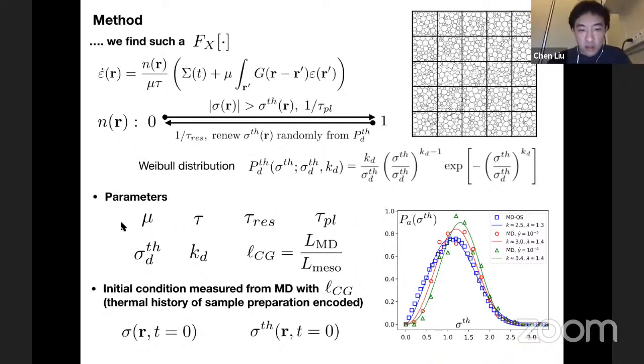So to summarize, we have these parameters. There are quite a lot. The first one is the shear modulus. The second one is the time scale that fixes the local viscosity when there's a plastic event. And these two time scales fix the stochastic rules of the local state. And these two parameters fix the shape of the distribution for the random local threshold that we draw from. And at the end, there's the coarse-graining length scale, defined as the linear size of the system counted in the number of particle diameters divided by the length scale, so the mesh size of the meso model. And this is a well-defined dynamic system,